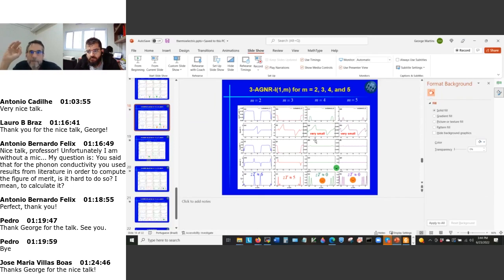So yes, there is a relation between the variation of sigma and ZT that is very strong, because you can obtain S in terms of, if I am not mistaken, the derivative of sigma divided by sigma. Here I am using another notation: the derivative of the conductivity divided by the conductivity. This Mott relation. I am almost sure that the Mott relation should be mentioned in Lundstrom's book. Otherwise, you can look for it in the literature, and you're going to find it. Okay, it's really interesting, because although for m equals 4 and 5 the conductivity itself is small, not as large as the other cases, its derivative is not small, and even though the ZT is small.